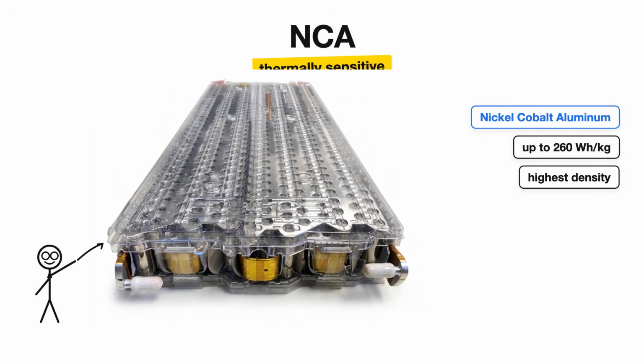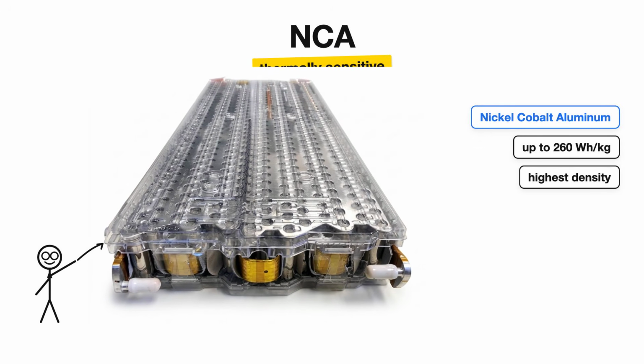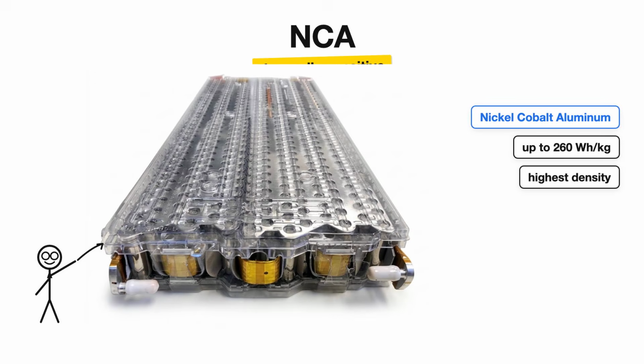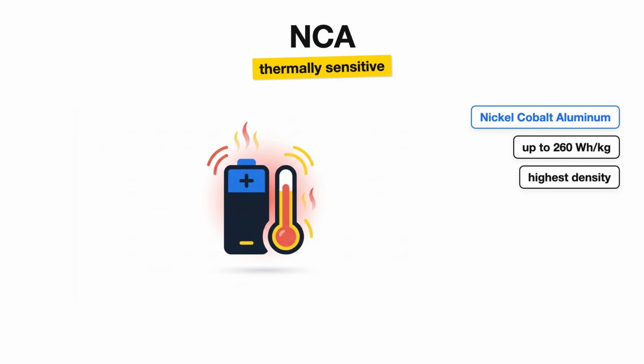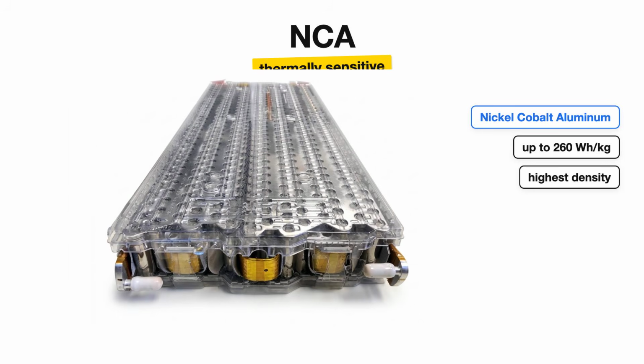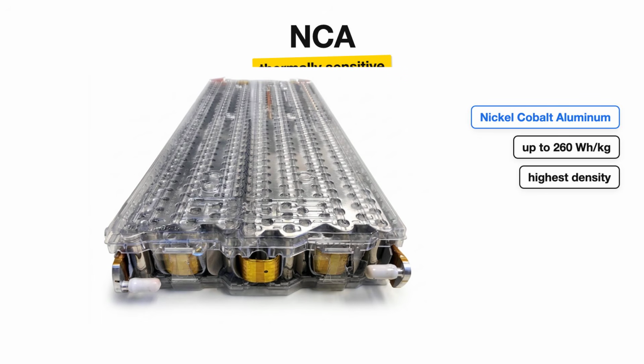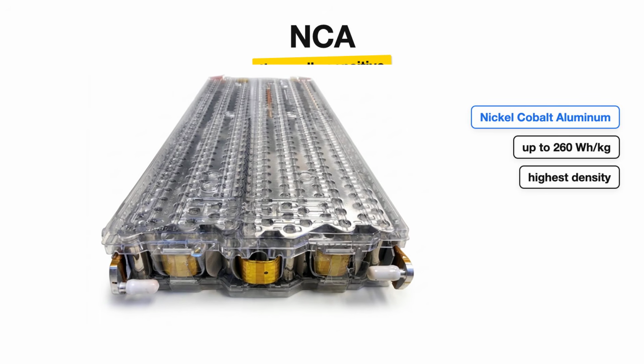NCA, nickel cobalt aluminum, is what powered the original Tesla Model S and Model X. Up to 260 watt-hours per kilogram, the highest density of any commercial chemistry. The trade-off was thermal sensitivity. NCA cells need precise management and do not tolerate abuse. Tesla has largely moved on from it.